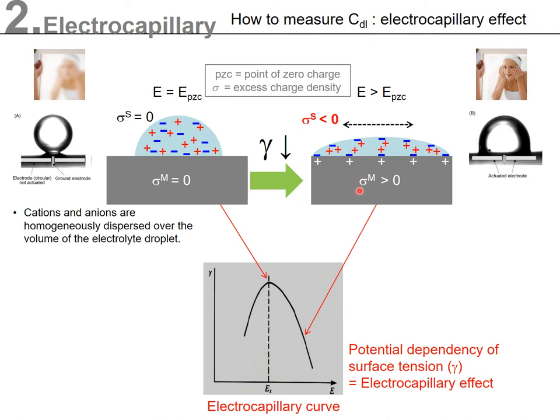Okay, let me change some potential. In the second situation, I have applied a positive potential, or also I could apply a negative potential. Then we could obtain this curve. The y-axis is the surface tension and the x-axis is the potential. So the surface tension is changing with the potential. At the point of zero charge, the surface tension should be maximized.